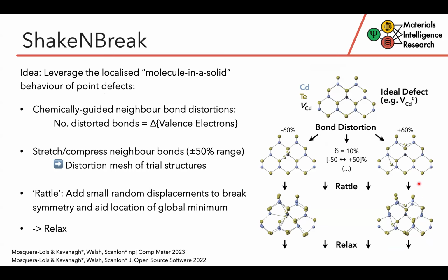But essentially, it involves two main steps of local bond distortions around the defect site with some level of what we call chemical guidance or chemical intelligence to try and do this as efficiently as possible, followed by rattling, so essentially constrained noise in our atomic positions to break symmetry. We also find that doing this really helps in aiding the location of the global minimum.